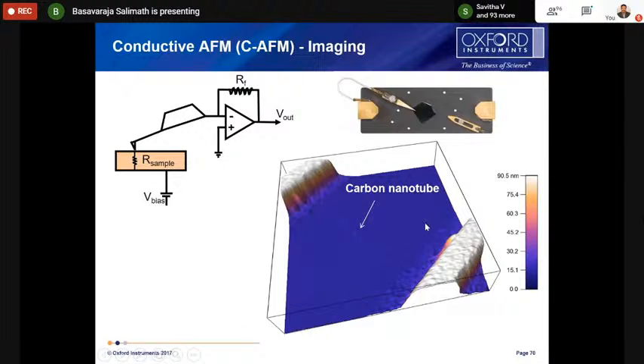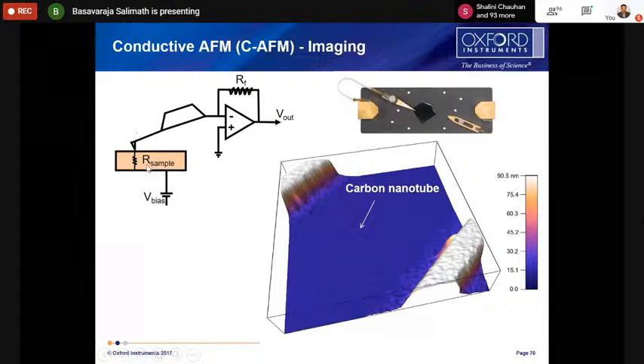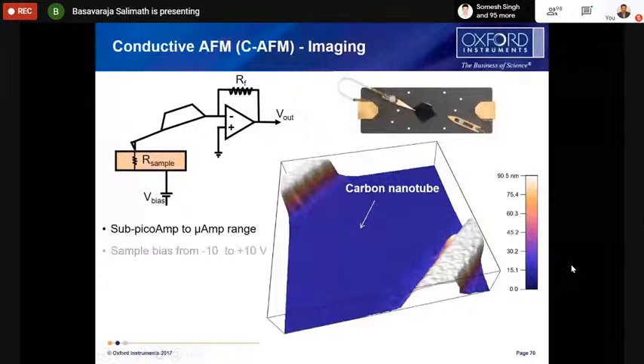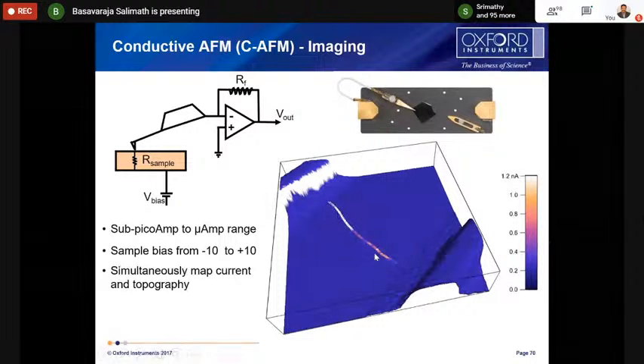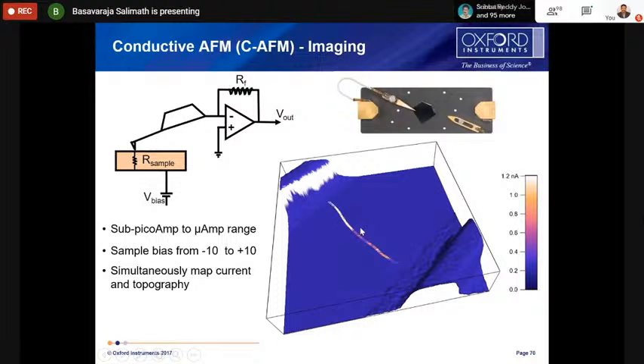In the same way, in the case of conducting AFM, here also we take a conducting tip, and in this case we are doing imaging in contact mode. I mean, the tip will be touching. So when you apply biasing to the tip, if you have a conducting region here, current will pass through this region. If you have a non-conducting region, current will not pass. So like this, you get some bright and dark spots in the image. You can see this is a topography image, a 3D image of the carbon nanotube. You can see it lightly, whereas in the conducting image you can see clearly, because here current is passing through, so you can see those conducting nanowires very clearly.